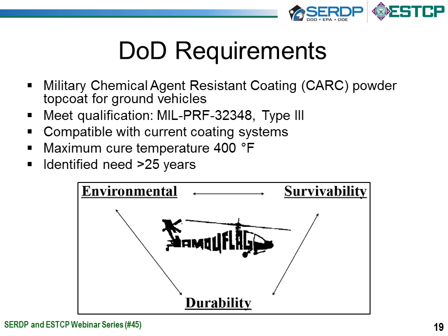With that said, some adjustments were made where we did determine that some changes had to be made, where you only use a powder coating under the powder coating top coat. So the liquid epoxy coatings that were out there as primers for liquid CARC were really not compatible with powder coatings, and that's a good representation of coatings manufacturers working with ARL and proving the point out, and then some adjustments made to the specification and the needs of the program. One of the key requirements was a maximum cure temperature of 400 degrees F, so that this is compatible with many of the alloys that are used in military.